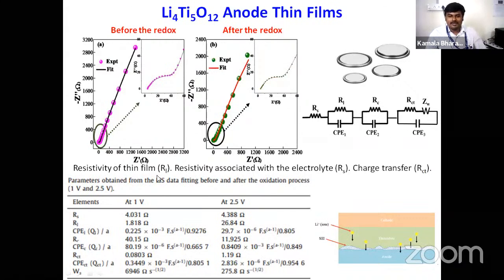You see there are several resistance components and capacitive components, right? These resistive components appear from the resistance of a film, and then resistance associated with the electrolyte, charge transfer resistance, etc. Capacitance generally arises because of the charge accumulation at various interfaces, like interface between cathode and electrolyte, anode and electrolyte, like that. So this impedance data tells us that after the first cycle, the charge transfer resistance increases. That is because at first cycle, usually the solid electrolyte interface forms, which increases the charge transfer resistance.